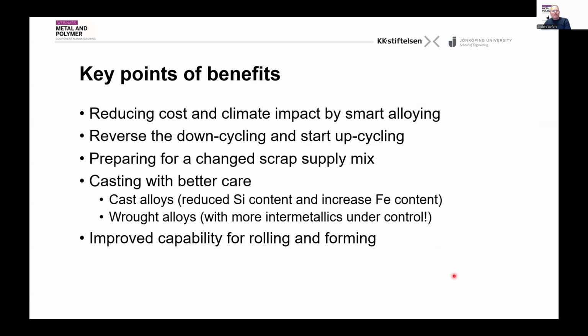So the key points of the benefits that we can see. One part is that we can reduce cost and climate impact by smarter alloying. We can reverse the downcycling and try to start working with upcycling instead. We can be more prepared for the change in scrap supply mix, because we know that what comes back as Zorba scrap will not be constant in composition. It will reduce in silicon content. And what we need to do is to cast with better care. So that means reduced silicon content, and maybe we can accept higher iron contents.